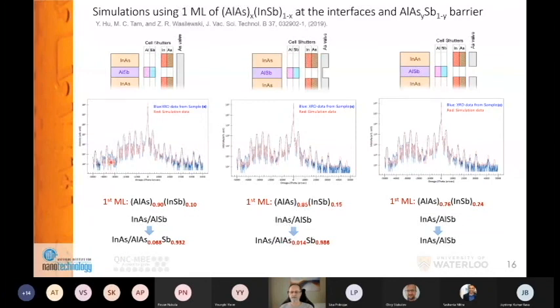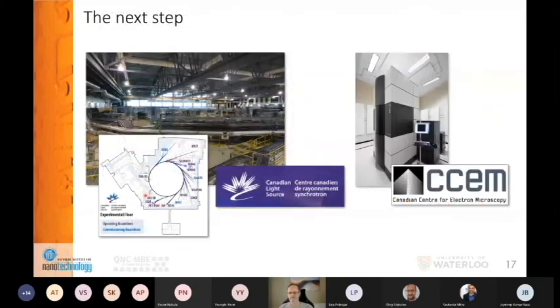We already know that indium can segregate, meaning not stay exactly where you put it, so it can walk out from the indium arsenide into aluminum antimonide. The antimony also is known to segregate, so the interface can become pretty complex. And so what we are now doing, we already booked one week in July at our Canadian Light Source synchrotron facility to use much better X-ray lines to peer deeper into the structures, including resonance scattering, where we will be able to identify the positions of the individual species there. So this is basically our next step here.